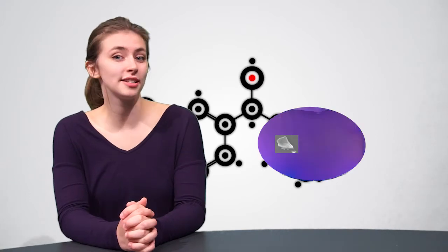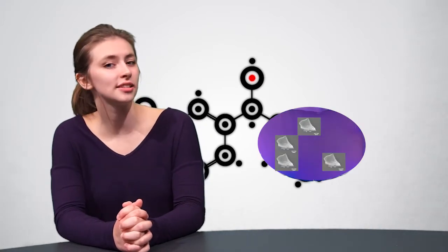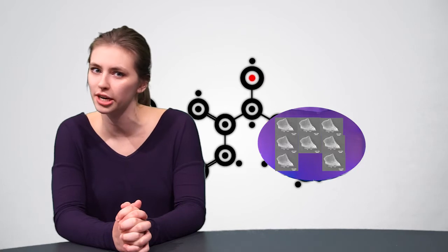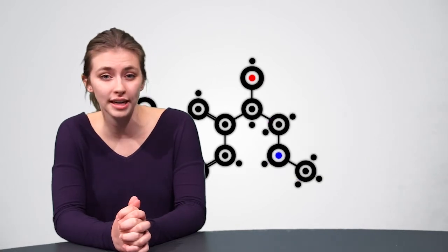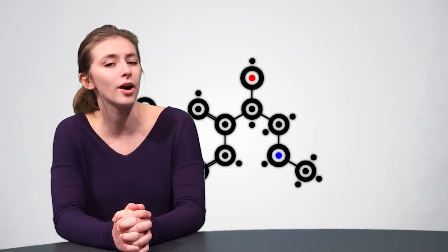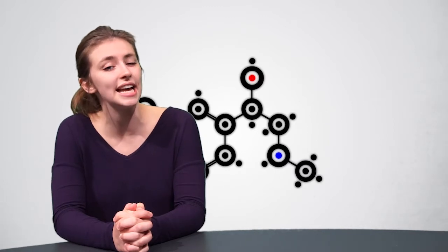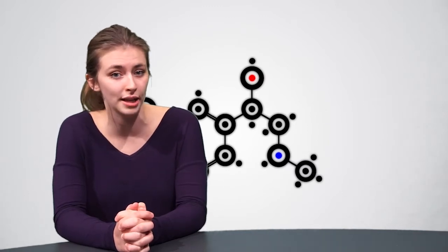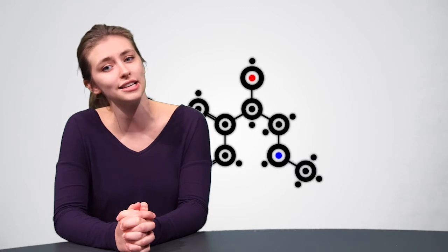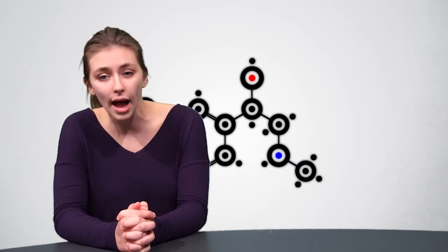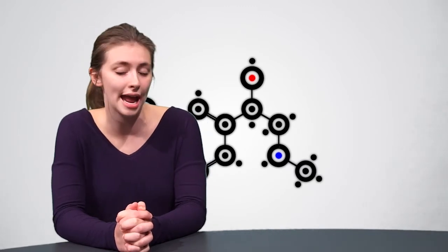P-type molybdenum disulfide flakes were synthesized on a silicon dioxide and silicon substrate. This all was within a modified chemical vapor deposition system where argon gas flow was maintained at the gas inlet of the larger quartz tube that contained the smaller tube with an end closed off by the substrate, as well as molybdenum trioxide powder and sulfur powder.